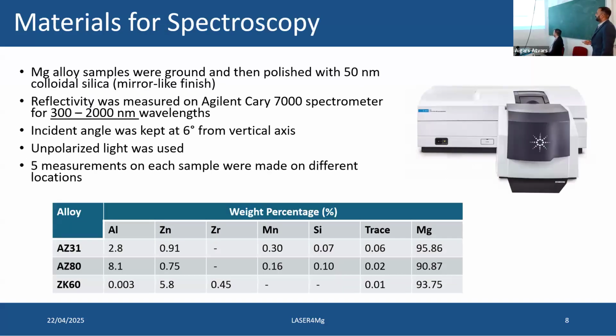So for the spectroscopy, this machine was used to measure the reflectivity. All the samples were polished to a mirror-like finish, and the Agilent Cary 7000 spectrometer, this machine over here, was used for wavelengths from 300 nanometers to 2000 nanometers. Here are some of the specifications of the testing, and 5 measurements for each. And here you can see the 3 alloys and their composition. So the AZ series has aluminum and zinc, and the ZK series has zinc and zirconium as the primary alloying elements.